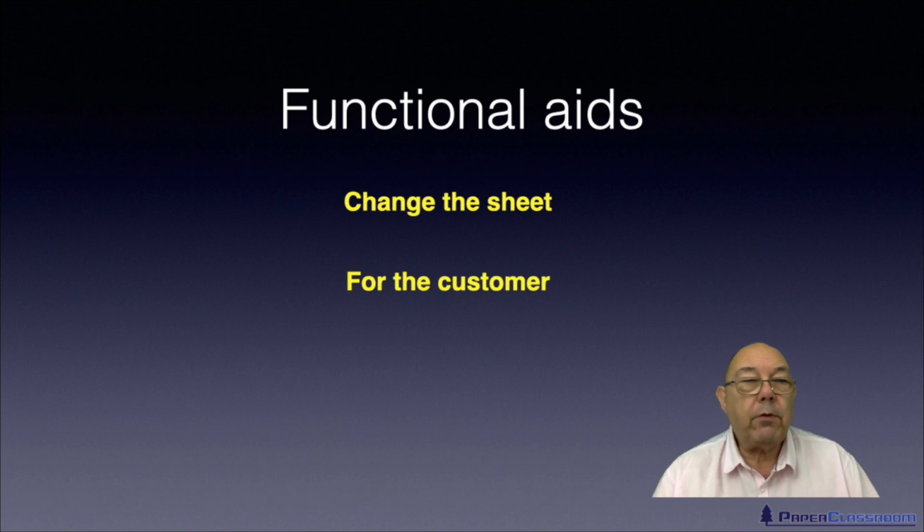If on the other hand we've got large amounts of froth and foam in our process and it's making froth spots in the sheet and it's causing holes and breaks, then we would add something to kill all that froth. We would add materials such as silicones or high molecular weight alcohols, and they would kill off all the froth and the foam.